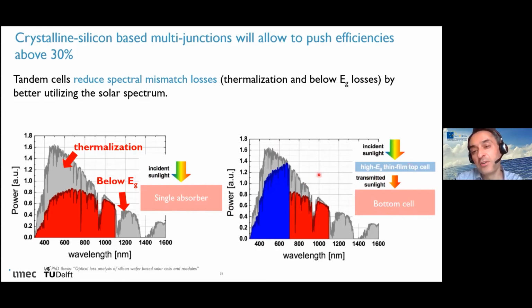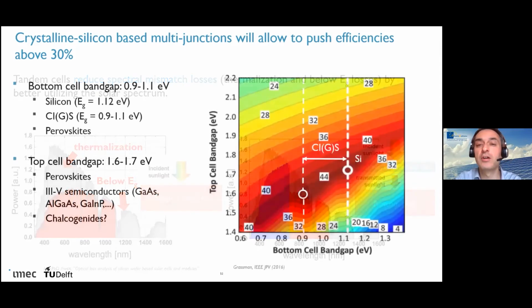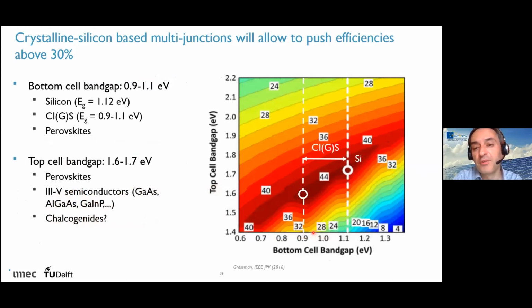The top cell will mostly work with the high energy photons, and the bottom cell will work with the low energy photons. If you then do the theoretical calculations, you see that for a double junction like that, the theoretical efficiency limit is above 40%, even up to 44%.